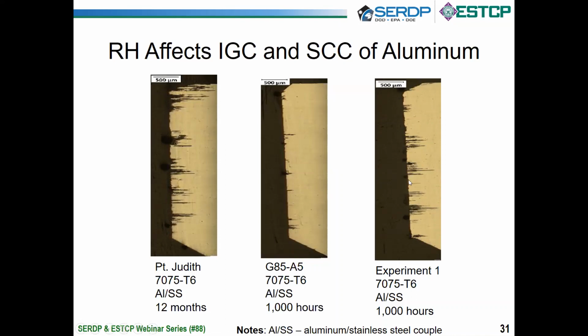And this was just a separate sample that we had and exposed it to an environment that was developed at the University of Virginia, and it's very close to the ASTM G85A2. The cycles are a little bit shorter. The main difference between these two environments is that the pH in here is dropped to about 3. Now let me note that you do not see any of this intergranular corrosion at all if you just put this in a B117. So the two things important: number one, you need cycles to initiate this, and if you want to drive it faster, you can change the pH in the solution.